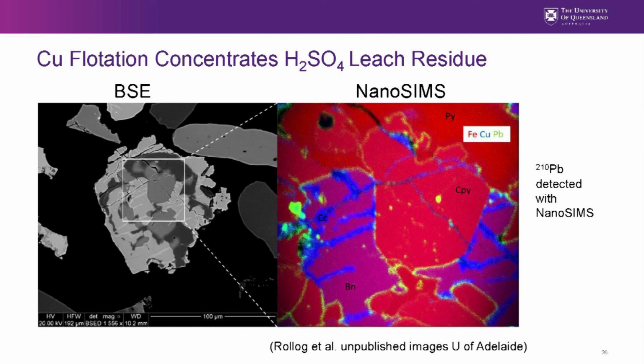And then here's some advanced characterization of some of these particles coming out of a concentrate leach step. Here we see a backscattered image of the particle, and then the same particle characterized using what's called the NanoSIMS in Western Australia, and that's a secondary ion mass spectrometer. Compared to EDS measurements, this can provide some resolution of very low concentrations of elements. One of the interesting things is the detector can be specific to 210Pb. In this case, most of the 210s were lead, and so we can see red is the iron, blue is the copper, it's the copper minerals, even chalcopyrite looks red in the way it's calibrated here.